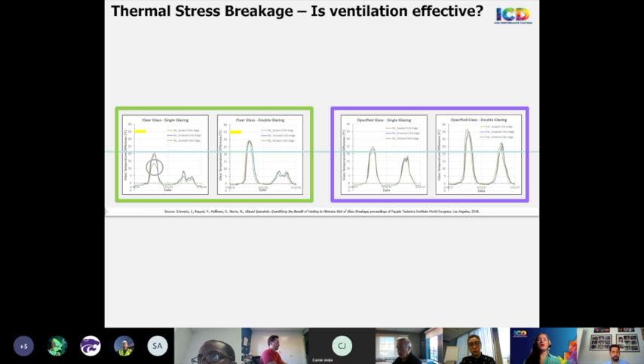Now comparing against the opacified results, looking at the condition for monolithic, the temperatures increase but are still below that 35-degree critical range. But for IGU, you can see they now start to reach out of that range. So there's a risk that can be dealt with by heat strengthening the glass, but adding a ceramic frit can take away some of that benefit, as we saw in Kayla's presentation. And I'll be showing a coating alternative in the next few slides.